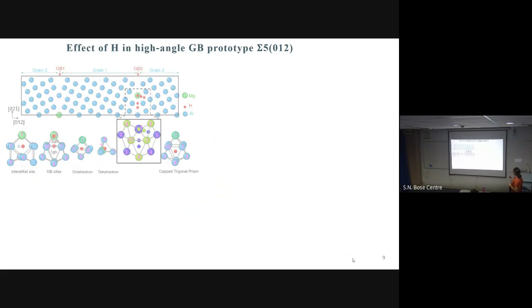So for the grain boundary study, I have typically chosen a high angle grain boundary, because high angle grain boundaries are the most commonly found grain boundaries in such microstructure evolution. And the prototype I have taken is a prototype sigma 5, which is a symmetric tilt grain boundary. And this is the simulation cell I have worked with, and the blue atoms are the aluminium atoms, and the green atom is the magnesium atom, and the red atoms are the hydrogen atoms. And these are the two grain boundaries.